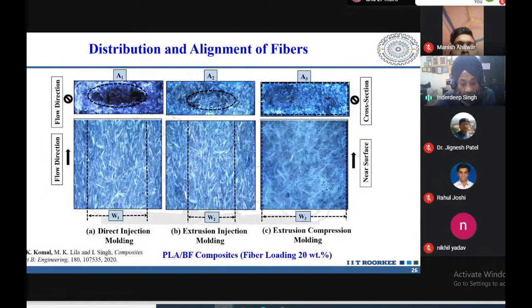These are some of the actual images of the samples made by different processes: direct injection molding, extrusion injection molding, and extrusion compression molding. So the polymer here is polylactic acid, and the fibers are banana fibers, and fiber loading is 20 weight percent. And you can see the reference here. This work has already been reported and published in Composites Part B: Engineering.